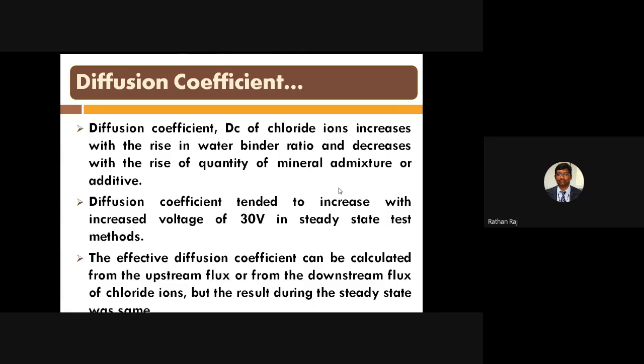When we talk about the corrosion, we should talk about the diffusion coefficient. The diffusion coefficient is denoted by DC, the DC of chloride ions. It increases with the rise in water binder ratio and decreases with the rise in the quantity of mineral admixture or some additives. So when we use additives like a mineral admixture replacing the cement, increasing the amount of the mineral admixture surely decreases the value of the diffusion coefficient.